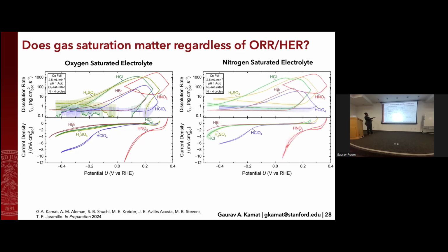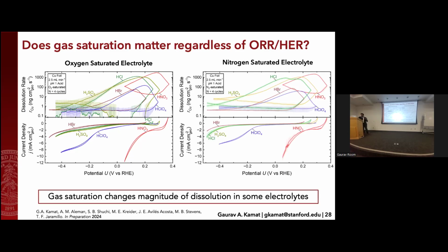density has sort of flattened out and it's gone closer to 0 current. And the only current that's happening here is based on either hydrogen evolution or other competing reactions. And you can also see very subtle changes to the dissolution profiles and also the magnitude of the dissolution. This is important to know because the gas saturation or the operational conditions also change your dissolution.